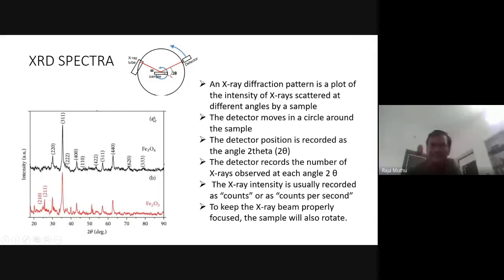Right. So how is it obtained? The sample is placed on the holder, and the sample is rotated with the speed of theta, whereas the detector will rotate at the speed of 2 theta, so that the focal point does not change. Then you can get the perfect focus, so it can detect the X-ray pattern. So please try to understand, the sample is rotating with the speed of theta, whereas the detector is rotating in terms of 2 theta. So this is what we call a theta-2 theta spectrometer, XRD, right? While doing like this, we will be getting the spectra.